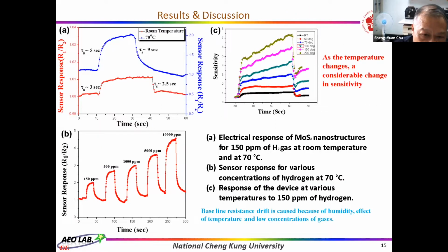These three figures: the first one shows the electrical response of the MoS2 nanostructure to 150 ppm of hydrogen gas at room temperature, and also at 70 degrees. We can see at room temperature, the response time is about 3 seconds, and the recovery time is 2.5 seconds. And at 70 degrees, the response time is 5 seconds, and the recovery is 9 seconds.